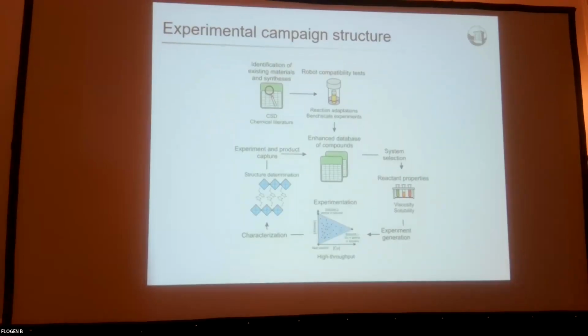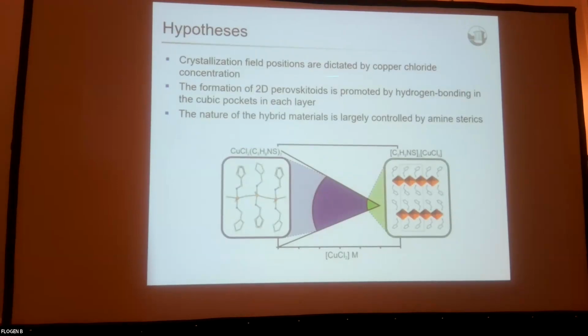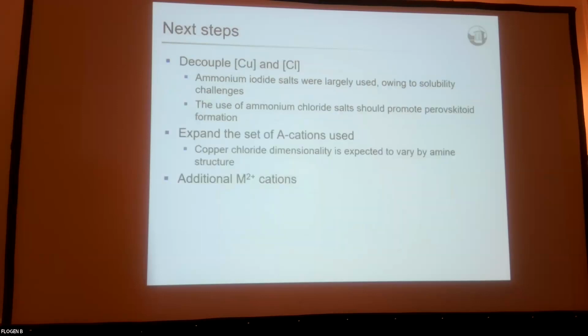And so this is sort of our first big circle through our approach, right? We've done 5 systems, lots of structural work, discovered a bunch of new compounds, and we can now articulate some of the hypotheses that govern the formation of these materials. And I would say that it is the copper chloride concentration that really matters most. Hydrogen bonding is important to stabilize 2-dimensional perovskitoids, and the way in which the hydrogen bonding preferences on these 2D layers work, it's this cubic pocket, which is important. And we need a sterically unhindered primary ammonium site to give rise to that stability, which results in the perovskitoid. And sterics, of course, affect the hybrids as well.